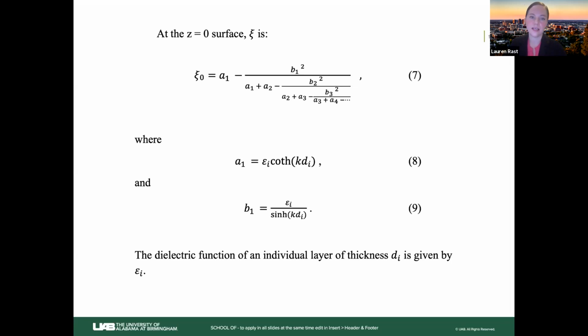So what I have here is an effective dielectric function for the stratified, so layered, heterostructure for a metamaterial. And it's extremely computationally fast. For a multi-layered structure, this kind of calculation will run in under a second on a PC. Okay, so this expression was first derived by Lambin, and the idea here is that we have a specular reflection type, like a mirror reflection type, model for a multi-layered structure.